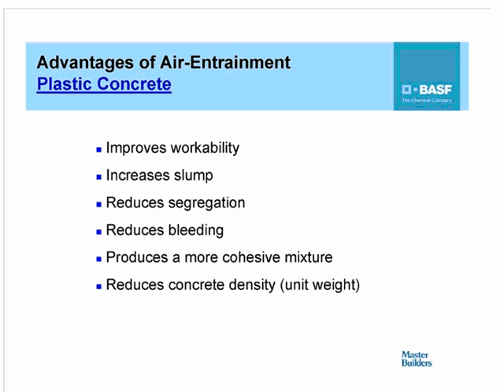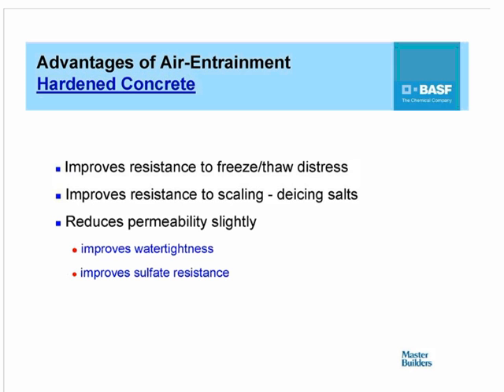Now, the benefits of air entraining admixtures in plastic concrete include improving workability, increasing slump, reducing segregation and bleeding, producing a more cohesive mix, and then also, in some cases, reducing the density of concrete. In hardened concrete, the main benefit is improving resistance to freeze-thaw distress, as well as scaling due to de-icing salts. Now, they also produce a slight decrease in permeability, which can result in improving water tightness as well as sulfate resistance. But for the most part, if we're interested in reducing permeability, there are more effective ways of doing so with high-range water-reducing admixtures and supplementary cementitious materials than using air entrainers within the industry.